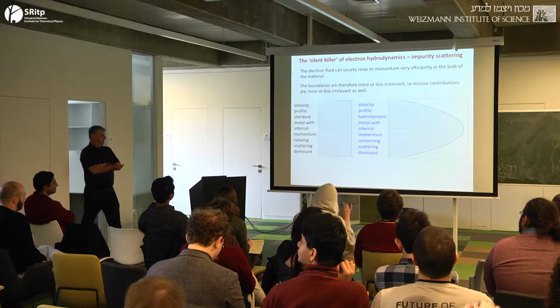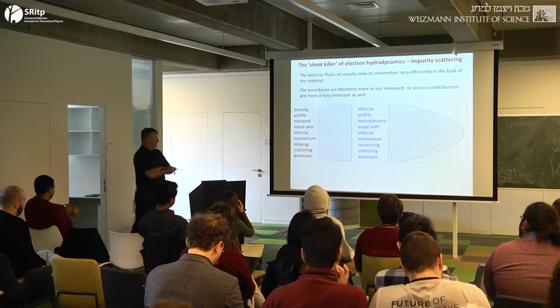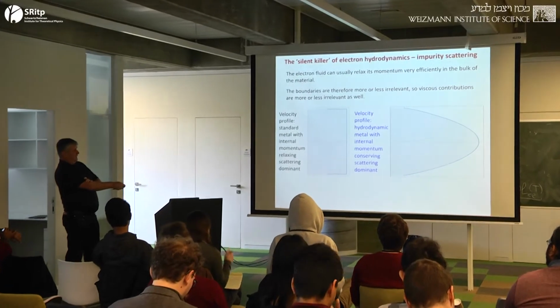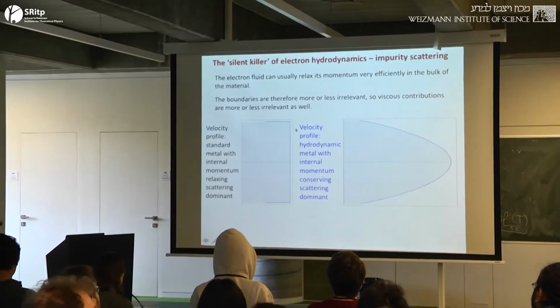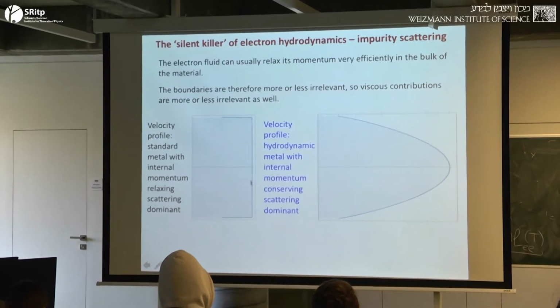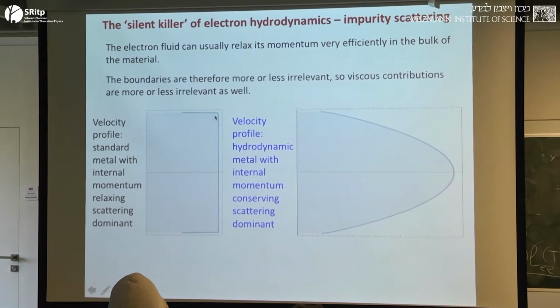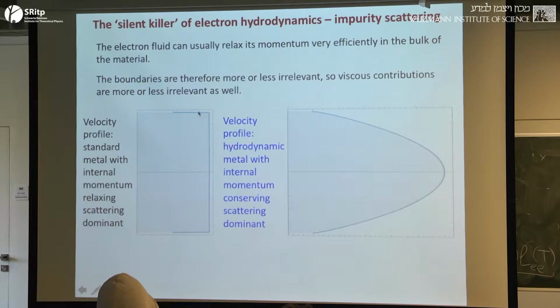Right. So, if we go back to velocity profiles, just to ground us again, if you're in the ohmic or bulk diffusive regime, then your velocity profile is going to be constant right across the solid, and if you're wide enough, this slight change in velocity at the boundaries is not going to determine what you measure in a flow experiment. Whereas the Poiseuille solution, as I alluded to earlier on, would have some kind of a boundary condition that would give you a velocity reduction at the edges, followed by a parabolic velocity profile.